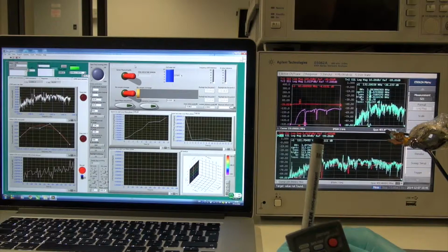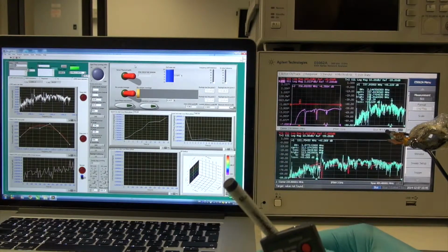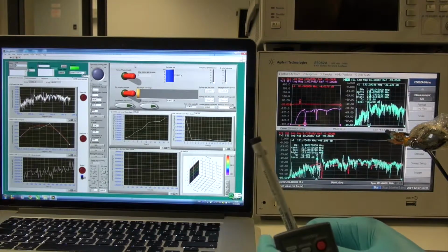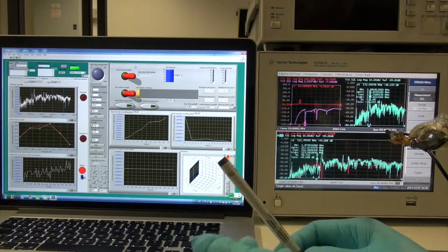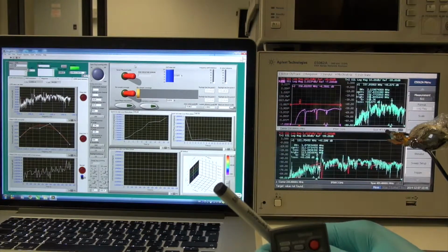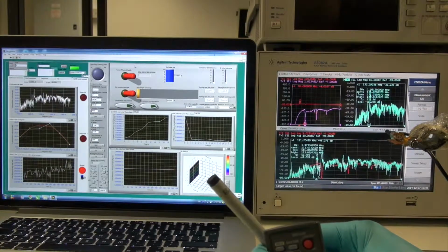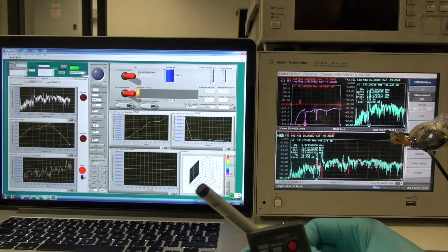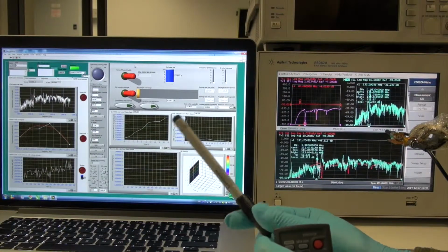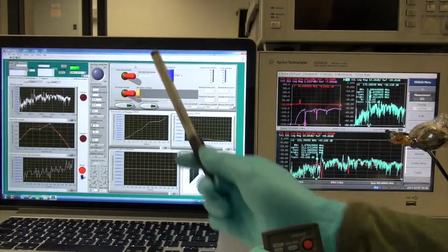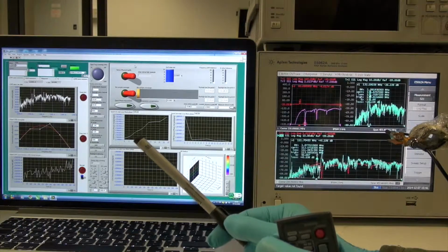Because the zinc oxide layer is vital in our device, when the microfluidic chamber is engaged, the solvent and the DI water inside of the chamber can dissolve or etch the zinc oxide layer, making it porous. So if the zinc oxide layer has been damaged, we can measure the extent of the damage by measuring the first order Love wave resonance peak without any liquid contact.